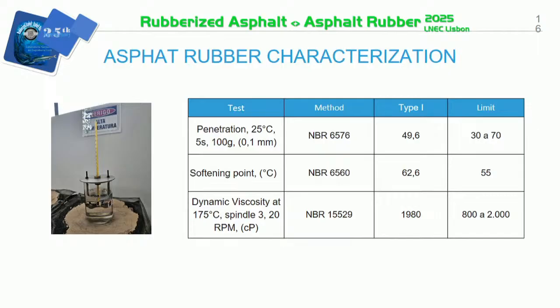The study focused on crumb rubber type 1, which exhibits greater elastic recovery and high polymer content compared to the other samples. The penetration value decreased, while both the softening point and dynamic viscosity increased, reaching nearly 2,000 CP.